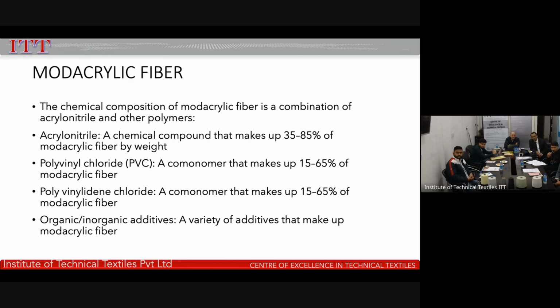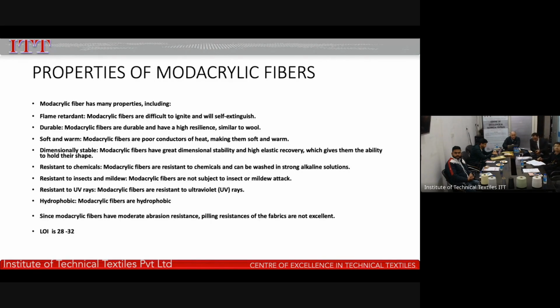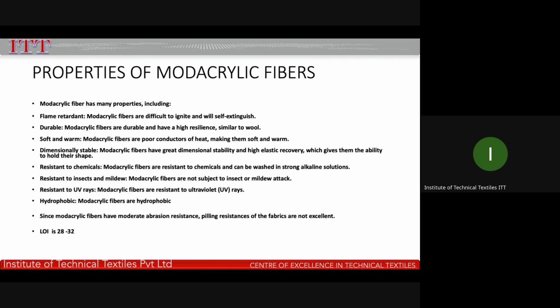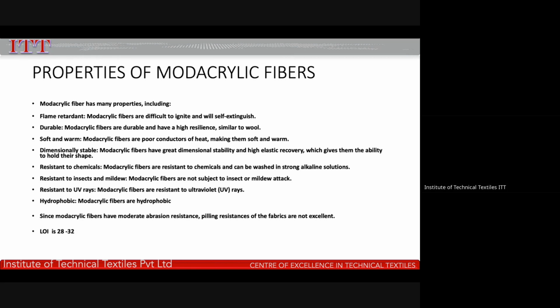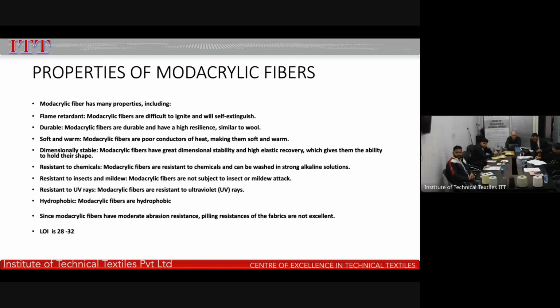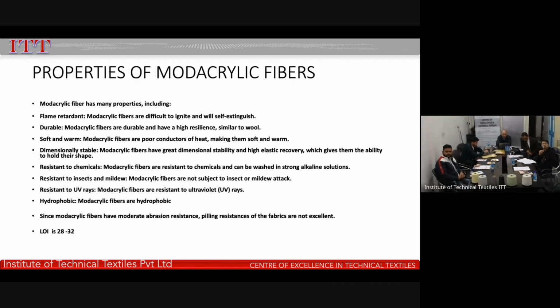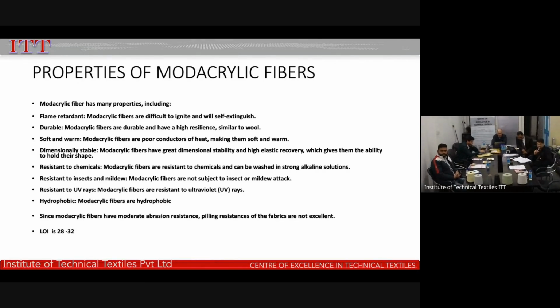Modacrylic is primarily around 45% acrylonitrile, and the rest of the component is a combination of polyvinyl chloride and polyvinylidene chloride. There may be certain additives added like antimony trioxide to it. Now, modacrylic fibers, as we say, they are inherently FR. They are difficult to ignite, but they self-extinguish. They are durable, have a high resilience, and are similar to wool. They are poor conductors of heat, but they are softer and warmer.